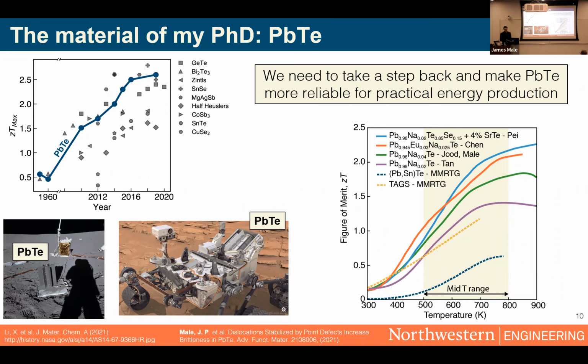However, you don't actually see these high ZT materials used for really any practical implementations. For example, the newest Mars rovers utilize lead telluride to generate power as well, but they actually have to use formulations more similar to that 1960s composition. This is due to a variety of reasons. So lead telluride has some issues with reliability, both making it consistently and also making sure it is mechanically robust. And also there's some reactivity and sublimation issues. So what I want to do is basically take a step back and use defect engineering to address some of those issues such that we actually can use this incredible material for practical implementation.